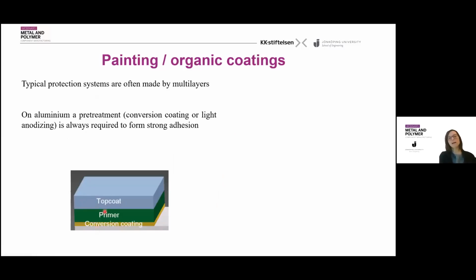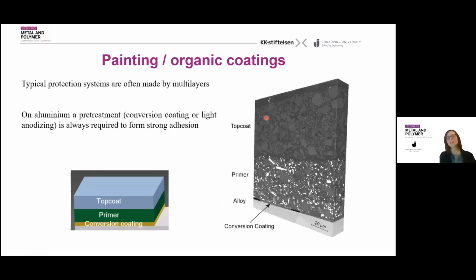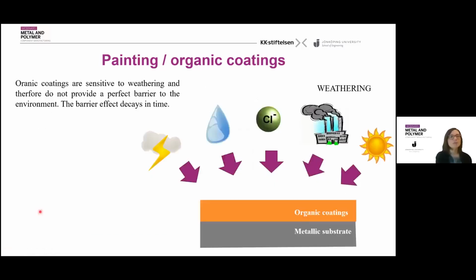Usually added as multiple layers on the conversion coating layer. And if you look into it, you can see that it has several components that you can choose. But a paint is not a perfect barrier, because organic coatings are actually permeable and sensitive to the atmosphere. Humidity, chlorides, pollution, and even UV rays from the sun can degrade the organic coatings. We call the sum of all this weathering.